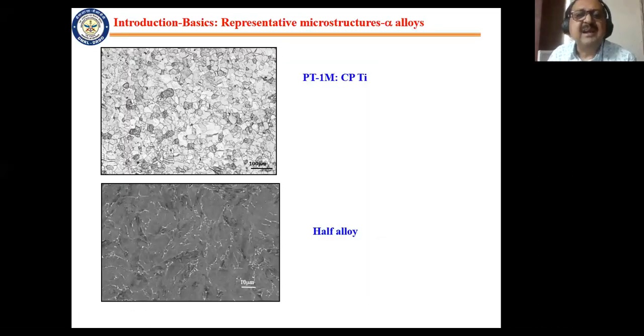I will again just introduce you to some of the microstructures. This is an alpha alloy. It's a Russian alloy. It is similar to commercial purity titanium. So it's a single phase, so it has to be etched to see the different grains. So this is a single phase, no second phase is there in this. And this is many times used for formability applications.